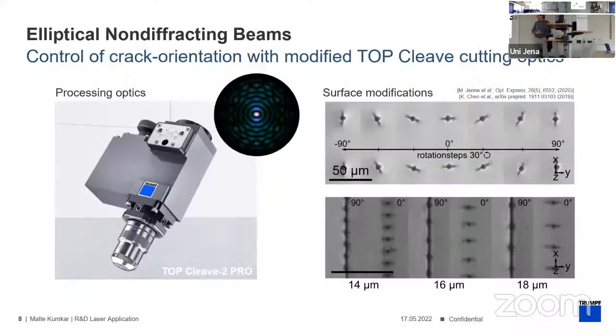Okay, so one thing especially helpful is the elliptical beam. The optics on the left is an optic where you can rotate the profile within the optics. By rotating this profile and inscribing the modifications, you see cracks coming directly from the modification, and they are oriented in the preferred direction of these elliptical profiles. If you then put several of these beams in line, as in the picture below, and the cracks are already aligned in the direction of the cutting of the contour, then they join and help separation.